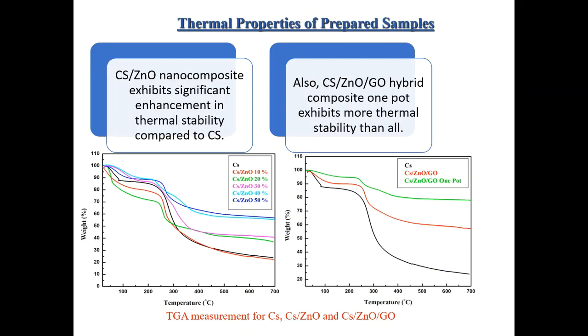Thermogravimetric analyses were conducted to study the thermal behavior of the prepared samples. These results show that the chitosan zinc oxide nanocomposite and chitosan zinc oxide graphene oxide hybrid composite had a higher residual mass percentage relative to chitosan due to the presence of zinc oxide and graphene oxide with the rise in temperature. In addition, a certain improvement in the degradation behavior of the composites was found relative to chitosan, changing from 22 to 79%, which could decrease the degradation of chitosan with increasing the filler, and the highest percentage was for the one-pot nanocomposite. So, the chitosan zinc oxide nanocomposite exhibits significant enhancement in thermal stability compared to pure chitosan. Also, the chitosan zinc oxide graphene oxide hybrid composite one-pot exhibits more thermal stability than all.